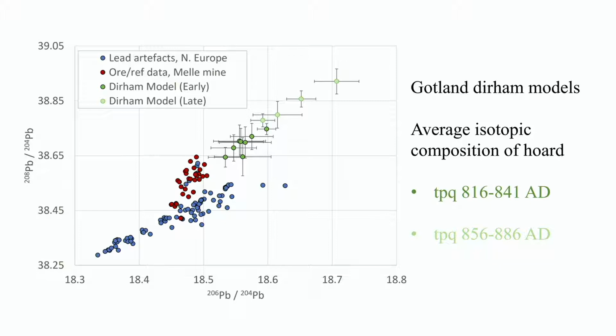Here you can see there's a shift in isotope ratios over time. I put here plus minus a standard error just to show a little bit about the diversity, or what the variation you would expect here is. So the early Gotlandic hoards form a small group, and it shifts up over time into the later 9th century because there are new mines that have been discovered, and these have different isotope ratios, and the proportion of this kind of silver is higher in the later phase. So we can actually separate early 9th century from late 9th century Islamic silver.